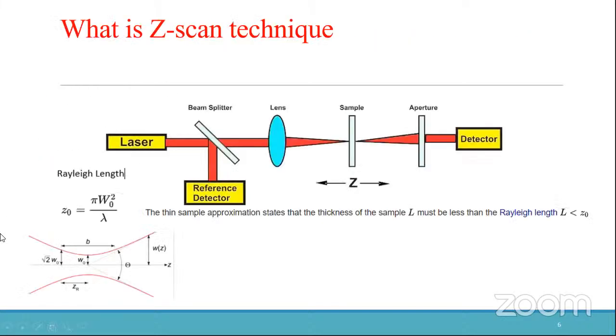In the Z-scan technique, we use a laser to scan the transmission through the sample, which is moved from minus Z to plus Z through the Rayleigh length. The Rayleigh length is given by this formula, where omega naught is the waist of the laser beam. In order to reduce the laser fluctuation, we divide the beam into two parts. One is used as the reference, and the other one is used to detect the transmission through the sample with a detector.